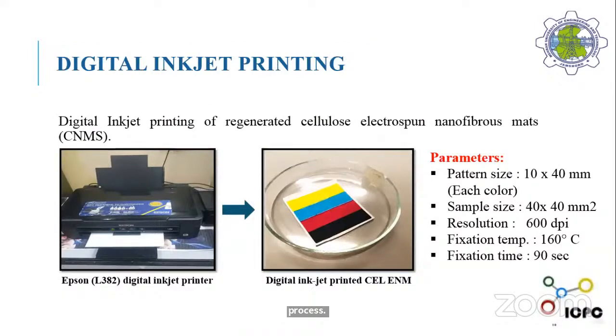For digital printing, an Epson L382 digital printer was used to print the cellulose nanofibrous mats. A pattern of 10 by 40 mm for each color was set, and the sample size was around 40 by 40 mm. Resolution was set at 600 dpi by 600 dpi, and the fixation temperature was around 160 degrees, and fixation time was 90 seconds. First, we use a paper. We paste the sample of cellulose electrospun nanofibrous mats onto the paper to support the printing process.